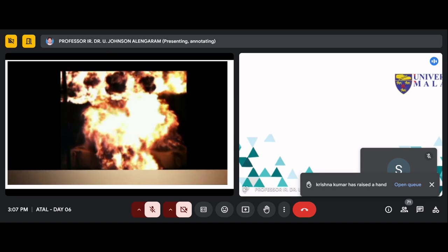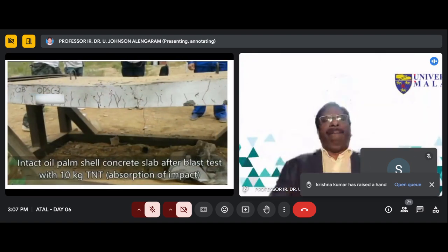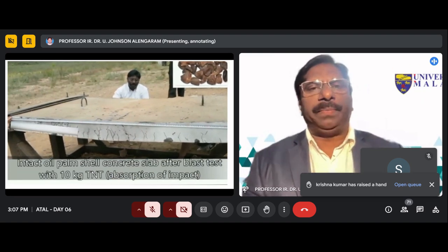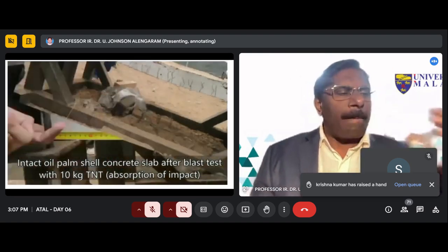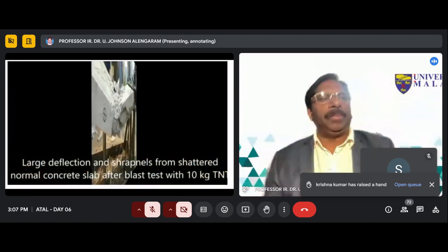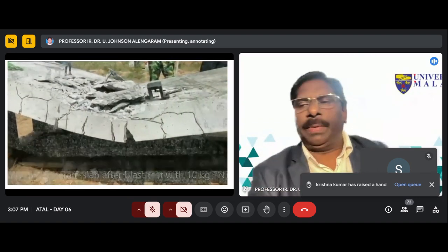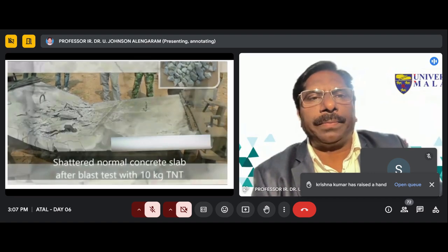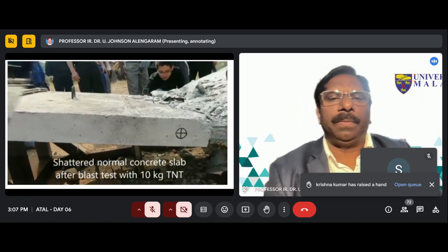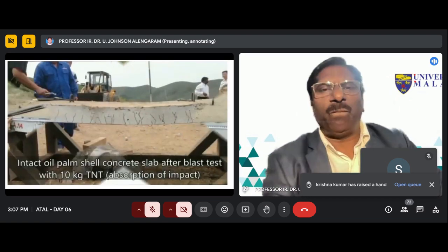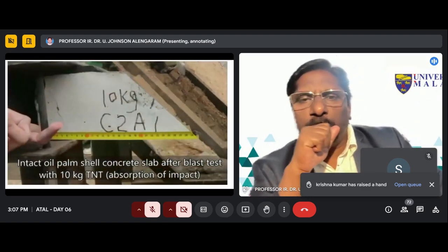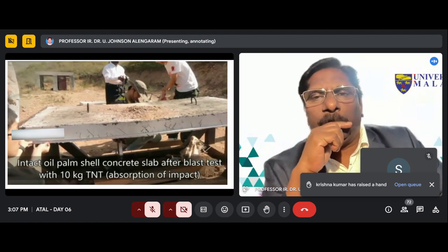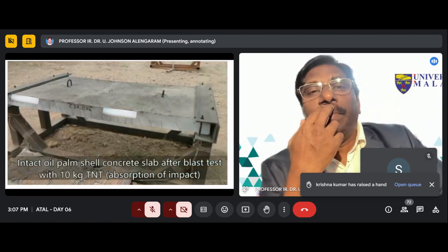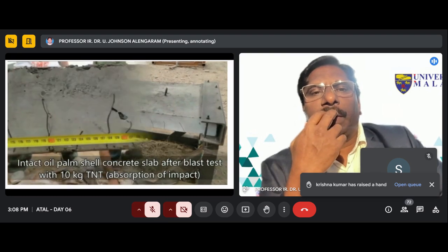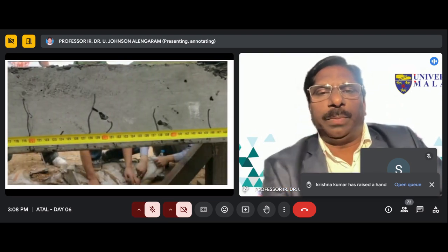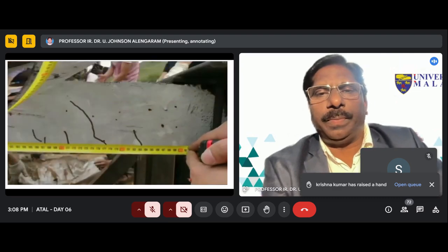After the blast test, the OPSC specimens showed ductility and impact-resistant characteristics such that not even a single shrapnel was found after the test on OPSC specimens. However, the normal concrete slabs couldn't withstand the blast test, neither the impact nor the pressure, and were completely shattered and damaged. There were a large number of shrapnel found from the shattered normal concrete slab. Thus, the research on OPSC slabs proved that OPSC could resist blast loads up to 10 kilograms TNT, despite multiple cracks and some deformation. The OPSC panels were able to resist the blast loads, and thus it paved the way for further research and commercial interest for future blast-resistant applications.